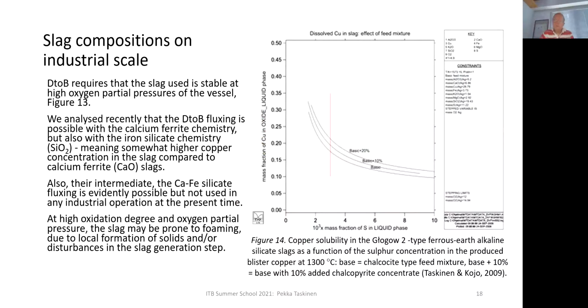So we have been analyzing what kind of slags could be used and will be used in these smelters, and it appears that these direct to blister smelters, depending on the feed material, can be run on calcium ferrite chemistry, but they actually can be run also with iron silicate chemistry if the gangue minerals are suitable. And then probably we can also use something which is called calcium iron silicates, those intermediates of iron silicate and calcium ferrite, which are not used in any smelter yet, but probably it may be possible.